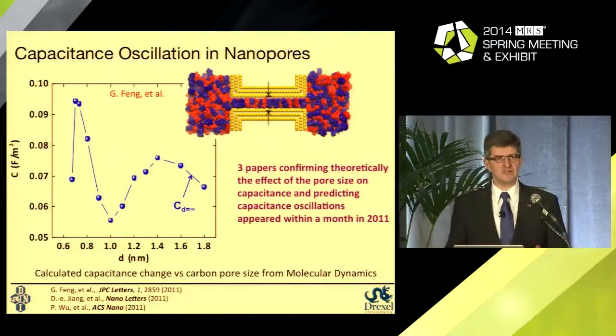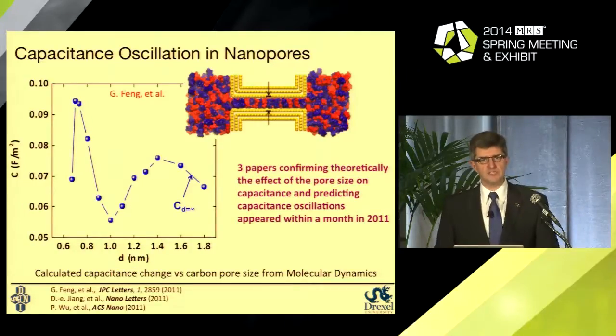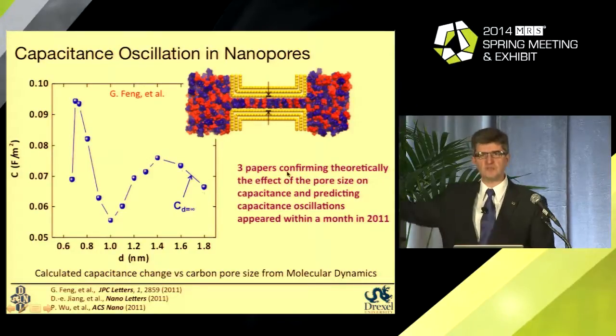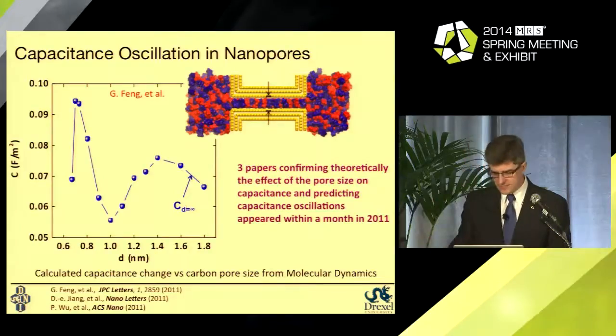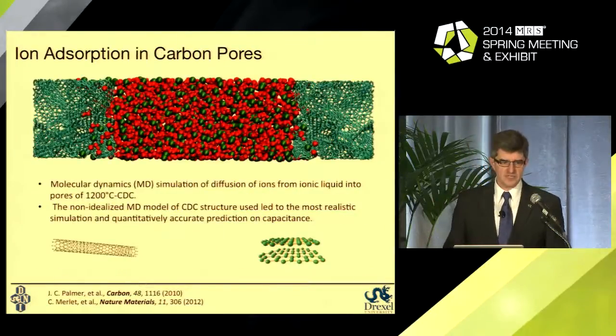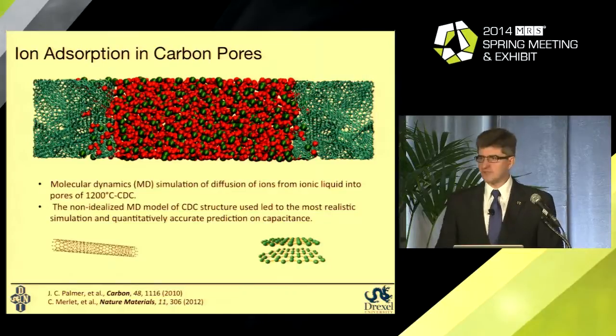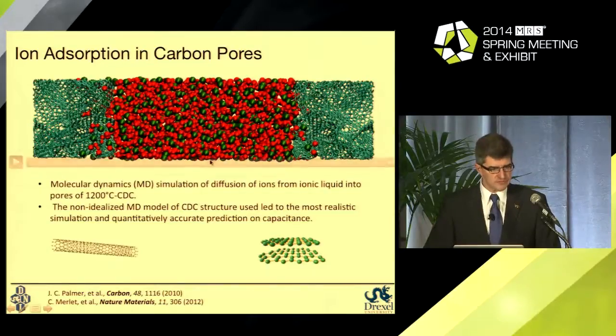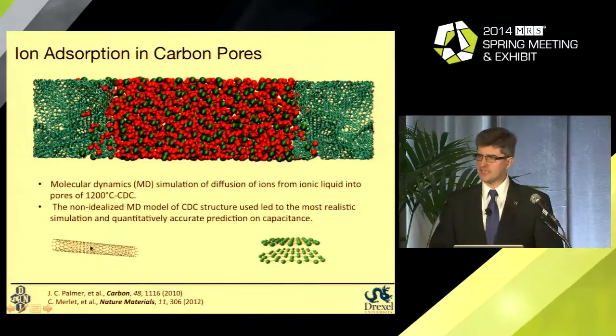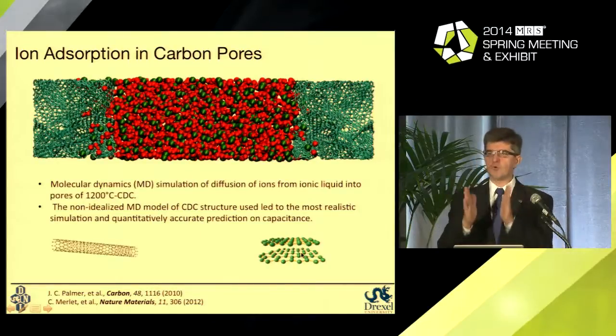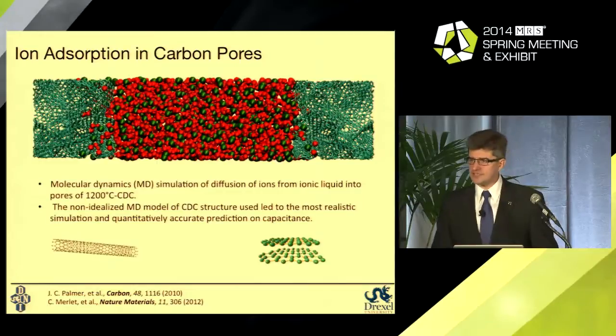And again, very similarly, modeling and simulation using molecular dynamics and DFT quickly confirmed, yes, there will be exactly this type of a peak at the pore size corresponding to the ion size. Moreover, there will be second and third peak oscillations of capacitance as 2 or 3 ions can go into the pore here. But what you would also notice, if you look at a variety of papers published by scientists who did modeling and simulation for this system, is that all of them were done either on cylindric pores, like carbon nanotubes, or slit pores, like in graphene or graphite here.